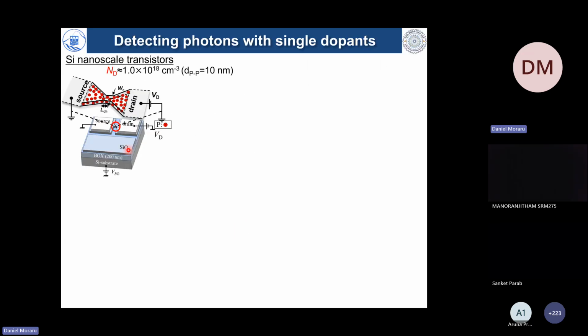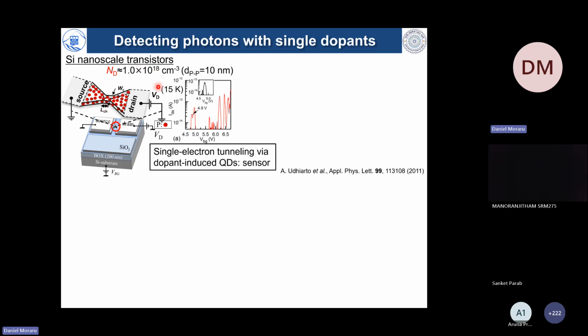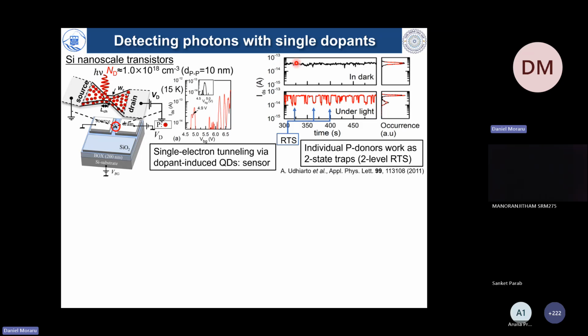This is a work that we carried out in a simple way. We tried to take this kind of transistors, mainly the transistors, and irradiate light on top of a channel for devices which do not have a top gate. So if we are at a low doping concentration, we could demonstrate by picking up this kind of current peaks and irradiating photons in the visible range, we could demonstrate that although in dark the current doesn't change, under light the current does change by RTS. And actually it's a two-level RTS, and as I mentioned before, this means that we are sensing photons converting into electrons, trapped and then released from dopant states.